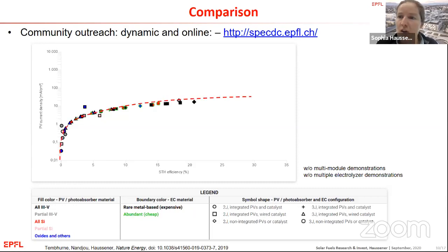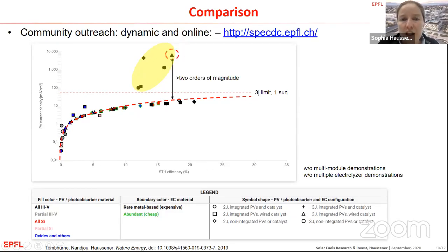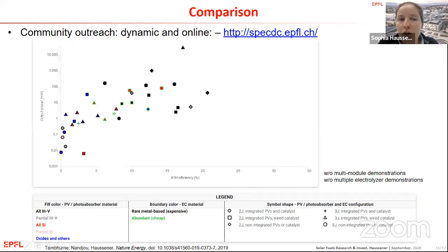Particularly, you can see here, everybody is converging or asymptotically reaching a limit. And this limit is in fact the triple junction Shockley-Queisser limit at 1 sun. And you can only push beyond this limit in terms of current density, which I show here on the y-axis, and efficiency if you use concentrated radiation. That's what we did. And here you can see our demo, which has 2 orders of magnitude larger current density than what typically is demonstrated. And this translates also into the power.